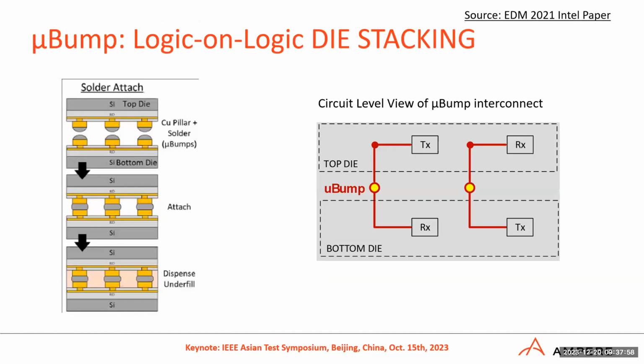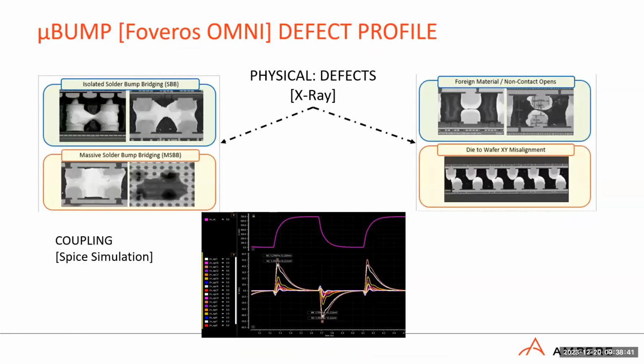But in this case, what really happened was that the microbump looks as follows. You have those copper pillars, then you put some solder on both of them, and then you attach them. Then there are other steps you do to clean this up and fill it up. So from a test point of view, this looks like simply an interconnect with a blob of solder in between. So we abstract it out at that level. We don't need to understand the entire processing. What we want to know is that the wires going from the transmit end to the receive end are actually working properly.